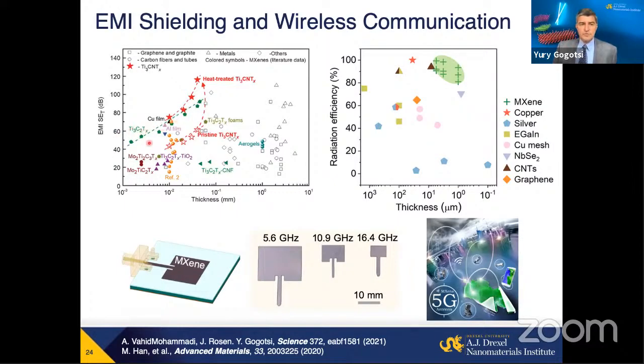And since we can produce freestanding films going down to 1 micron, and this film can provide about 50 decibels, it means that 99.999% of waves in the X band will be reflected or absorbed here. So we can make much thinner shields for electronics.